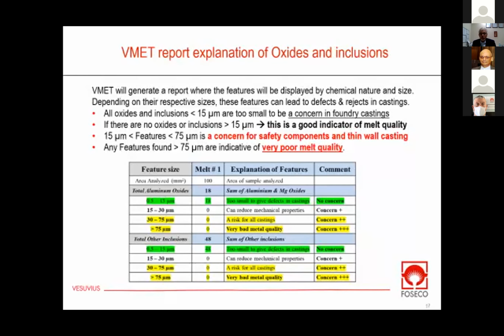And so, what we know from experience is that if you have an oxide smaller than 15 micron, usually it doesn't give a defect in a casting. I have never seen in my 20 years in Foseco a casting that was rejected because of a 10 micron oxide or inclusion. But what we know is when the size of these oxides increase, so typically the yellow range there, 75 micron or larger, this is when we start having leakages.